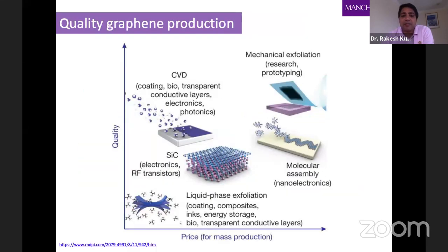So if we compare the quality of graphene with the synthesis method, we find that the high quality we get is from exfoliation, mechanical exfoliation, or molecular assembly, but they are expensive. On the other hand, for large scale fabrication or synthesis of graphene, the CVD is the method where we can have a large scale fabrication. But the problem with that is that we still have very little control on the quality of that CVD